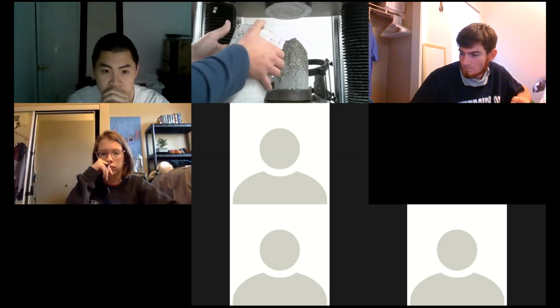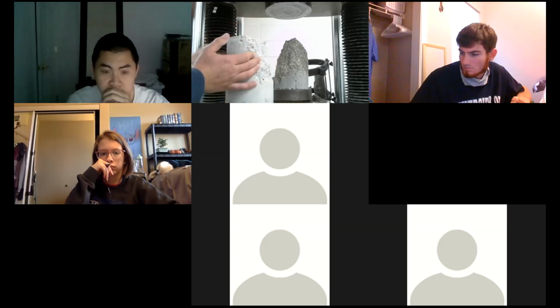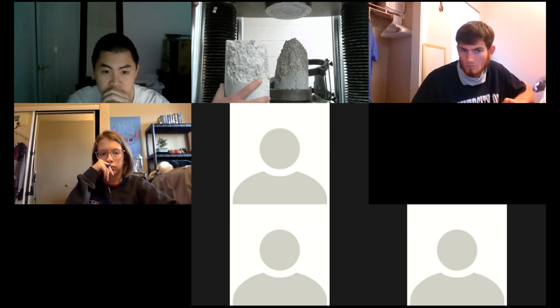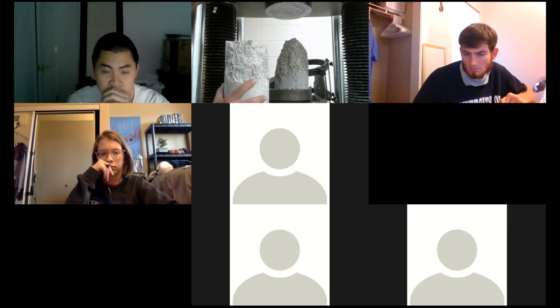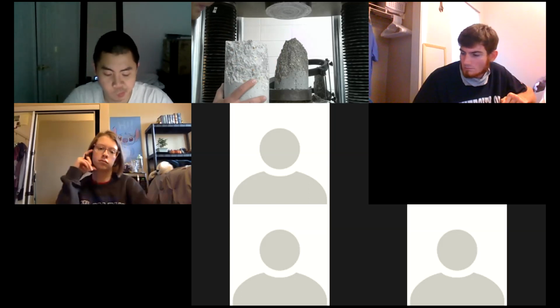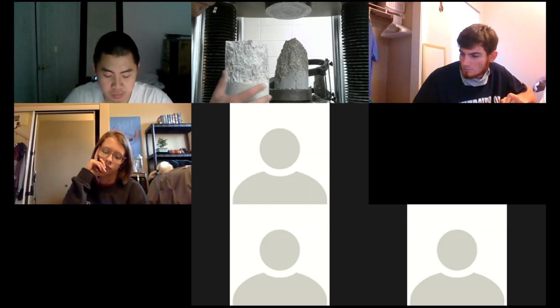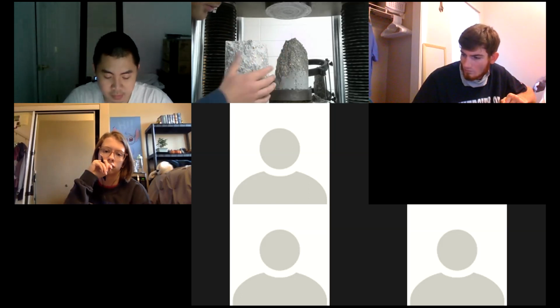Jace was here and Tuan was here at the beginning of the class. I tested this concrete. This concrete has been curing for over 6 or 8 months. I don't know the exact time, but it's from last semester. I went up to 200,000 pounds, which is way over 70 something thousand that we got for our sample.